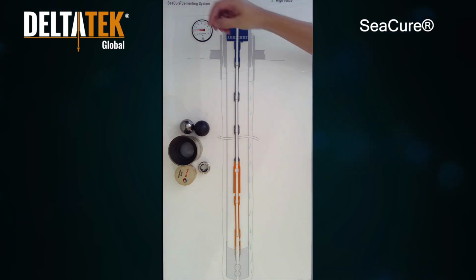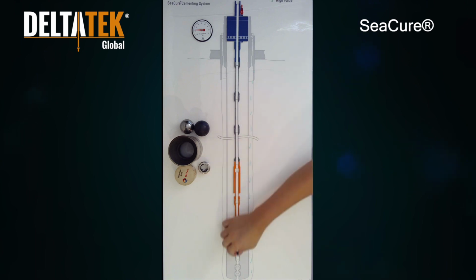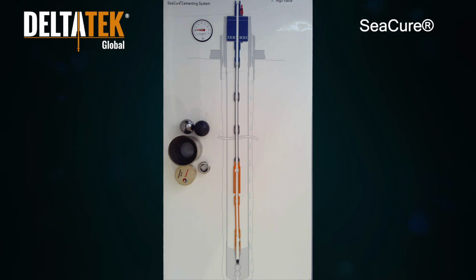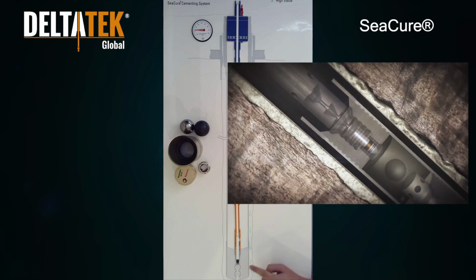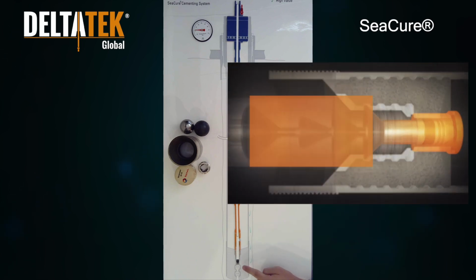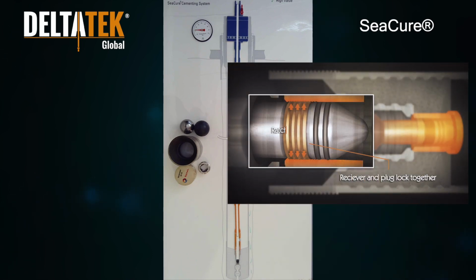At the end of the cement job, a lockdown wiper plug can be launched into the string and chased with slurry to guarantee good quality cement around the shoe. It's important to note that the lockdown wiper plug effects a bi-directional seal after it bumps because of a ratchet mechanism built into the nose on the plug and corresponding receptacle in the shoe.